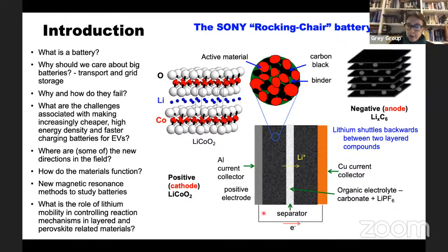And the point of this slide really is to illustrate that it's much more complex than just having a cathode material and an anode material. You've got to think about an organic electrolyte that's going to be stable enough in the very reducing potentials of lithiated graphite. So that's almost as reductive as lithium metal itself. It's only 75 millivolts higher than lithium metal at its most reduced stage. You've got to have current collectors, aluminium on one side, copper on the other side.